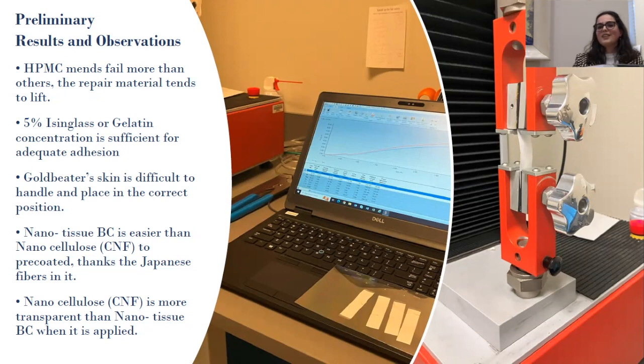These are some of the preliminary thoughts, results and observations that we made. HPMC tends to fail, so it tends to lift instead of remaining attached to the parchment support. Isinglass and gelatin at 5% usually are sufficient, because we also tested the same adhesives at 8%. But usually 5% is sufficient to remain adhered to the parchment support. The goldbeater's skin is very difficult to handle. And in comparison, nanotissue bacterial cellulose, the one that contains Japanese fibers, is more opaque than the film that contains only nanocellulose fibers.